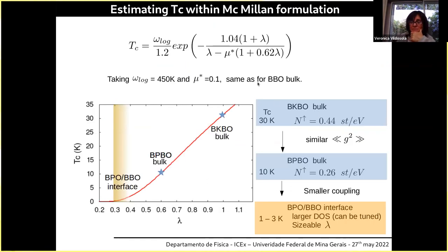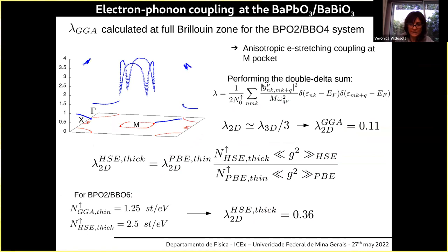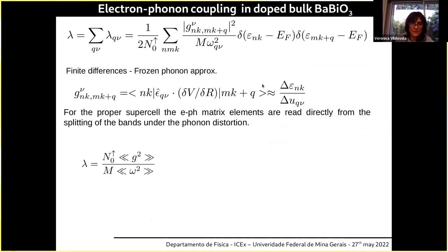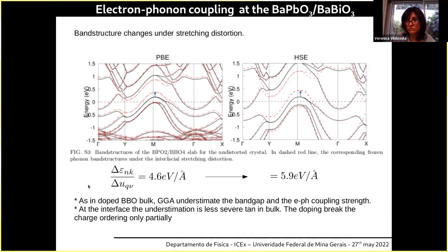The lambda, or better here, here, lambda. What we observe is that at the interface, this factor decreases as compared to bulk, but this one increases a lot. When the width of the BBO layer is larger, the density of states is larger, and the coupling and the temperature will be higher because the coupling is higher. That is what we understood.